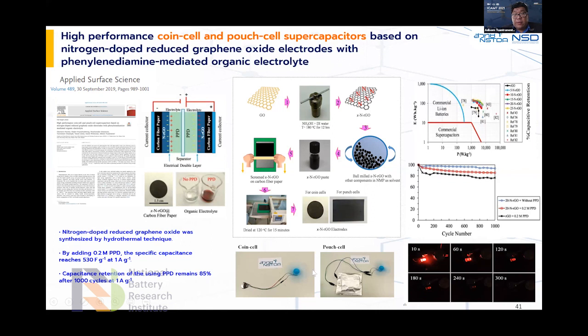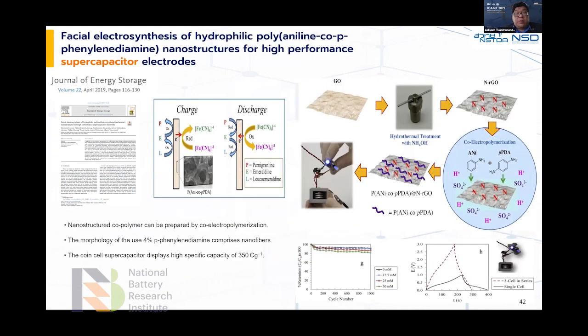We can demonstrate it compared to the commercial lithium-ion battery and commercial supercapacitor. And we also play around with the facile electrosynthesis of hydrophilic polyaniline co-doped with polyphenylenediamine nanostructure on the surface. So we can enhance the performance of the supercapacitor close to that of batteries.